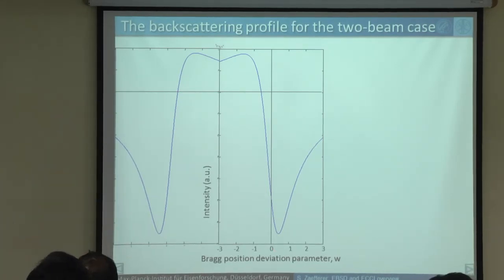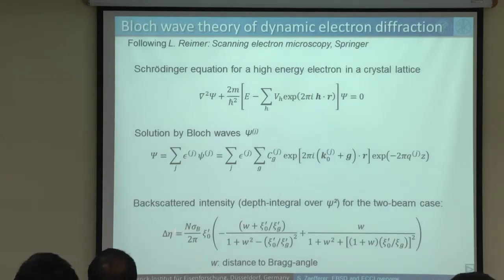It tells us in principle which intensity we get depending on how far away I am from the exact Bragg position. Bragg position means W equals 0. Then the wave is traveling exactly at the Bragg angle, and if I'm at a different angle, then W has a value, either positive or negative. And I can solve this equation here. Here is the W, and I get the intensity. And if I solve that and plot it, then I get this picture here.